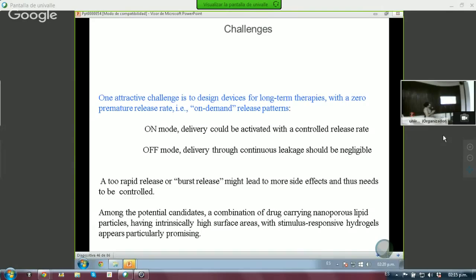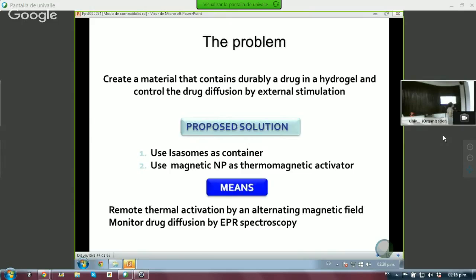What I'll be presenting to you here is a choice of a combination of drug, like we did last time. This drug is carried by lipid particles, which have a very high surface area, and they have stimulus responsive hydrogels. These hydrogels are in a way replacing the polymers that I showed you yesterday, which were wrapping around these drugs. In this case, what we used is a hydrogel. So it's also, of course, biocompatible, and this approach, we feel, is particularly promising.